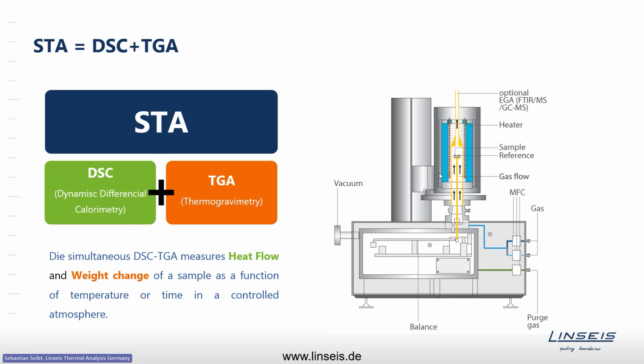This schematic drawing here shows how the typical setup looks like. So here you can see a thermal analyzer containing a thermobalance unit in this lower part. So you have an in-house manufactured balance cell that is a beam balance in a monolithic block out of aluminum or out of stainless steel, typically. And this beam here is fixed in one pivot point in the middle. On one side, you have a physical counterweight. On the other side, you have a connector pin where a sensor rod is connected to. The complete beam is monitored by infrared light diodes, so the exact position of the balance beam is recorded quite constantly and in a very narrow range.